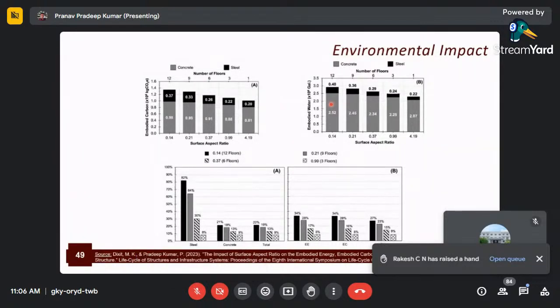This figure here presents a comparison of the results with respect to the single-story building. So we are comparing the low to high-rise or low to medium-rise building structures with respect to that one floor structure. The A plot here shows the variation in the contribution of material quantities for the different aspect ratios that we considered. And we can see that the total quantity of steel significantly reduces as we decrease the number of floors, while the decrease in the quantity of concrete is somewhat lower.